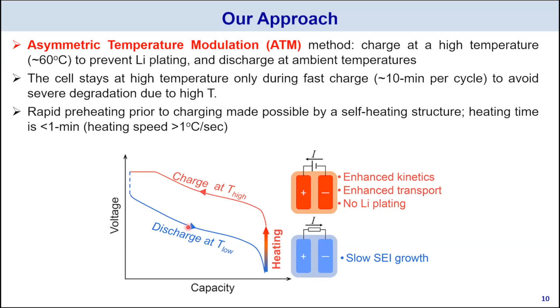Now, how do we do fast charging? It's different from the literature, other people's work. It's a physics method based on the so-called asymmetric temperature modulation. And it can be illustrated here. We basically leave the battery alone during operation, let's say rest or discharge, as usual at ambient temperature. But whenever you bring an empty battery to a fast charger, we give a quick preheating to an elevated temperature like 60 degrees Celsius. And then at that elevated temperature, we enjoy enhanced kinetics and transport, and therefore eliminate lithium plating, and then do the 10 minute fast charging. Finish it up, and once it's done, the battery will naturally cool down and you go back to your normal business of operating the battery.